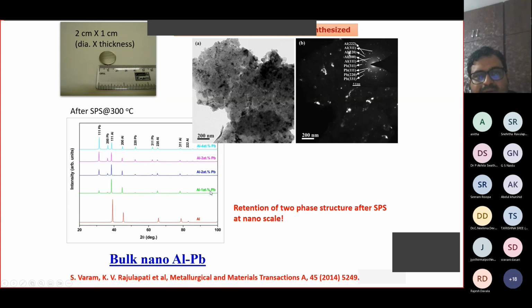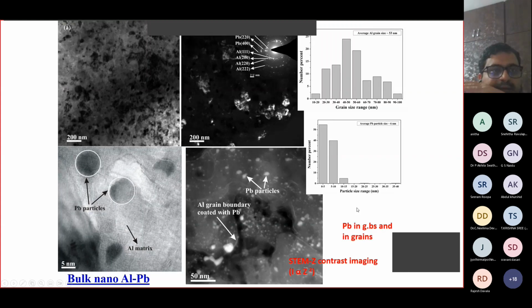Here it's pure aluminum. When you add 1% lead, you see that you have the presence of lead peaks in X-ray diffractograms, and then with the increase in lead further up to 4 atom%, we have the increase in the intensity of the lead peaks as well. That shows that aluminum and lead have remained as two different phases intact even after subjecting to high temperatures during spark plasma sintering. And this work, and the associated mechanics of plasticity, we published in Metallurgical and Materials Transactions in 2014.